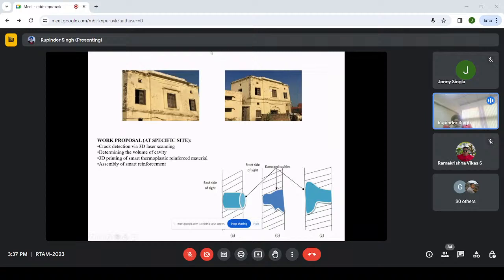And what is the problem? Let me share. Let us say this is the heritage wall, and this side of the wall is accessible to me, and this side of the wall, which we call the back side, is not accessible to me, and in between I have a crack, right? Then there is a second case in which the entry side of the crack is large and the rear side of the crack is small. Then there is a third case when the entry is small and from the rear side the crack is a little larger. For these three different cases, I need to have a different type of treatment.